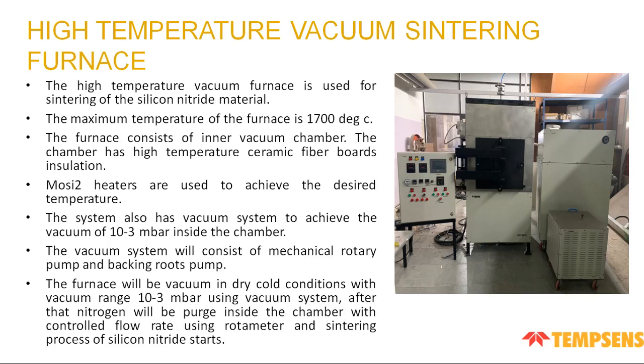This is the bigger, similar furnace with a higher temperature range. This furnace has a temperature range up to 1700 degrees centigrade, and the vacuum achieved in this furnace is 10 to the minus 3 millibar. This high temperature vacuum furnace is used for sintering of silicon nitride material. The maximum temperature of the furnace is 1700 degrees centigrade.